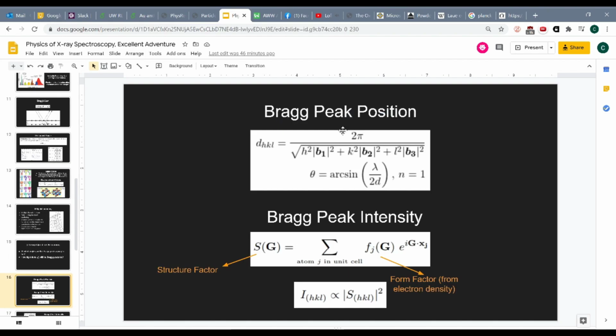So the Bragg peak position, we can find from the distance between the planes. We have D, we solve for theta using Bragg's law, and like I said, you just take the arc sine of lambda over 2D. We're going to assume that we're using only one integer number of wavelengths. You technically could have multiple, but for our purposes, our wavelengths are small enough that we're only going to get one full wavelength between both of our lattice planes.